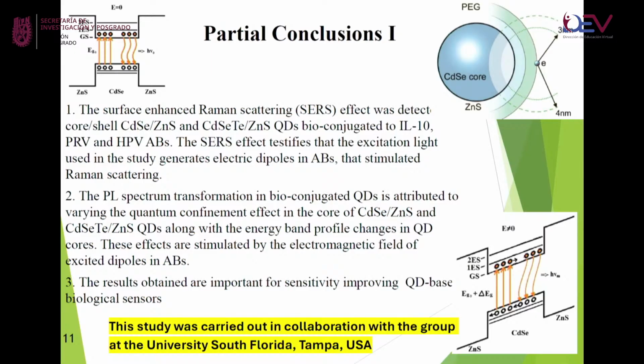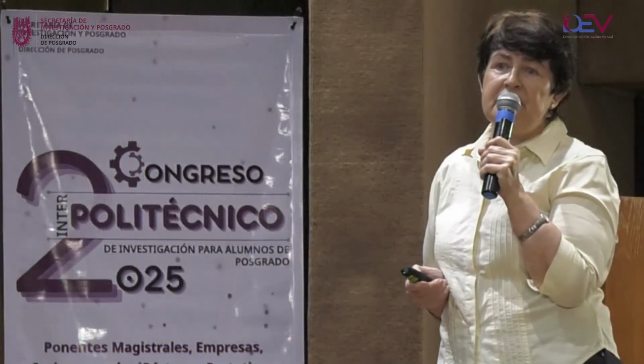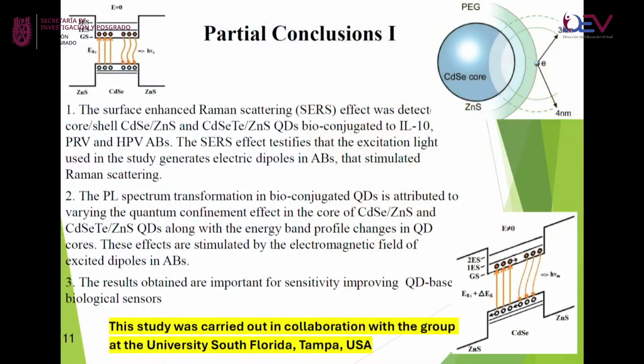The surface-enhanced Raman scattering effect was detected for very different antibodies and very different quantum dots, and this effect is connected with the generation of electric dipoles in the antibody that stimulate surface-enhanced Raman scattering. The photoluminescence spectra transformation in bioconjugated quantum dots is attributed to varying quantum confinement effect in the core, as it looks like the electrical dipole shifts electrons from the surface and effectively decreases the size of quantum dots. And this effect is stimulated by the electromagnetic field of excited dipoles.